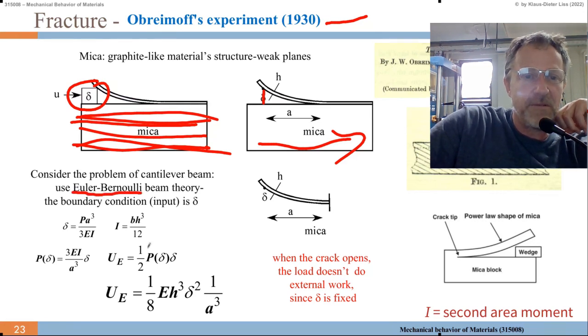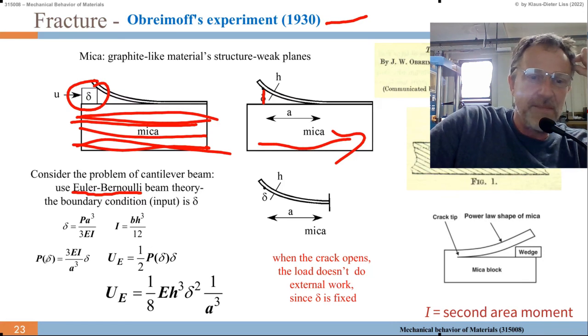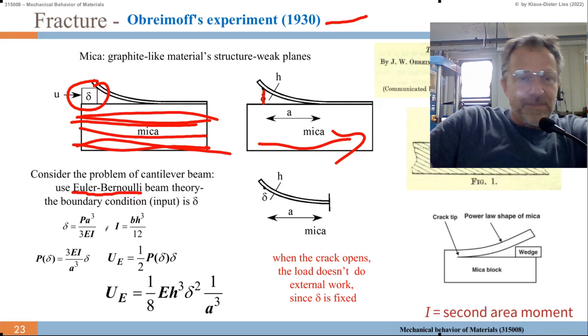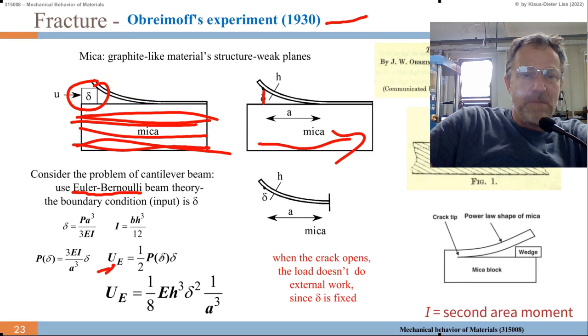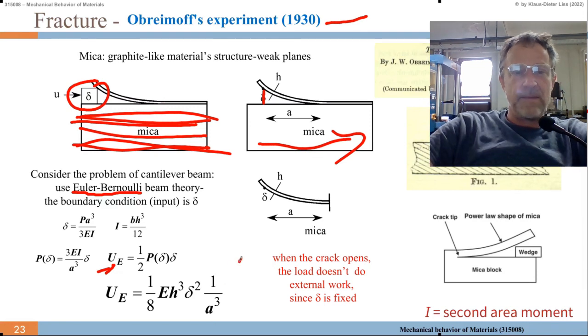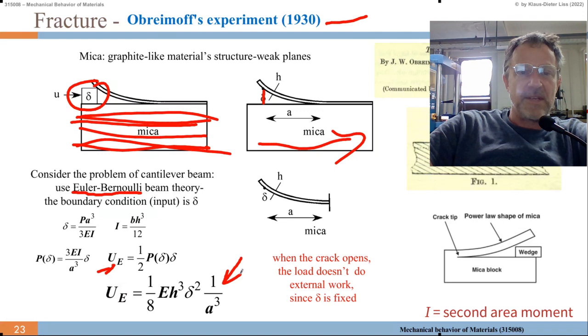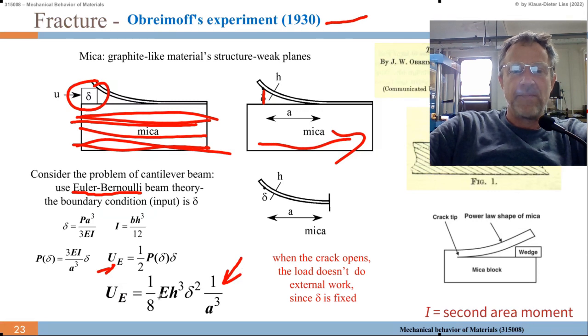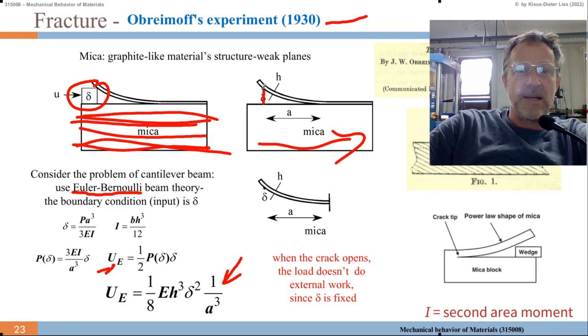As I said, we have to rush through it. And we get eventually the elastic energy equals 1/2 P times delta times delta. Or UE equals, when you work it out, 1/8 E H to the 3 delta squared times 1/A to the 3. So what is important here is the 1/A to the 3, because A is a variable - all the others are constant in this given experiment. 1/8 is constant, E is constant, H is the thickness given by the experiment, and delta is how much I lifted up, also given by the experiment.